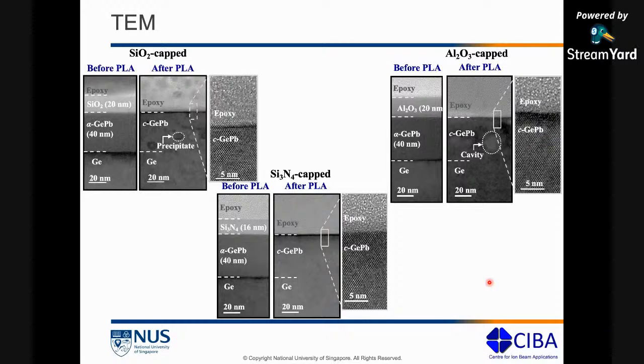So this was our conclusion for this project, that pulse laser annealing works to some extent, but not to the extent that we were hoping it would, in keeping lead inside the germanium, so that we can convert the germanium lead to a direct band gap semiconductor, right?